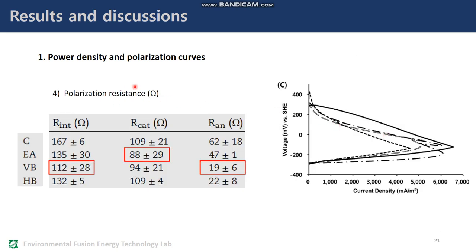Polarization resistances for electrodes and a full cell were calculated from polarization curves. Anodic polarization resistances were 62 ohms for C, 47 ohms for EA, 19 ohms for VB, and 22 ohms for HB. The brush anodes showed 25 to 43 ohms lower anode resistance than the carbon cloth anodes.